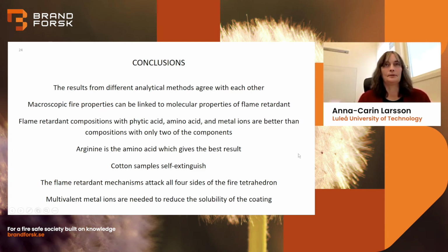The flame retardant mechanisms attack all four sides of the fire tetrahedron, and when we add the multivalent metal ions, we can reduce the solubility of the coating.